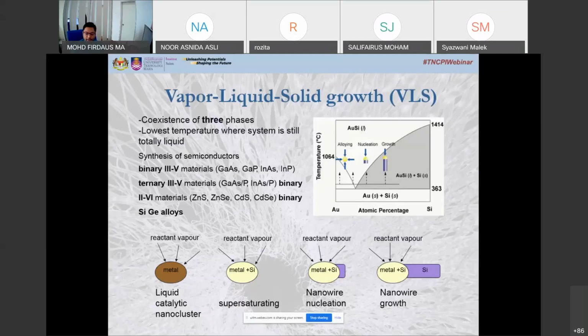So what happens is, initially the gold particle is deposited on the silicon substrate, which results in the formation of a gold-silicon droplet at a specific temperature. The melting point of the gold-silicon alloy at the eutectic temperature is very low compared with silicon or gold themselves. So the formation of a silicon-gold droplet on the silicon surface from gold particles is only possible above 363 degrees Celsius.